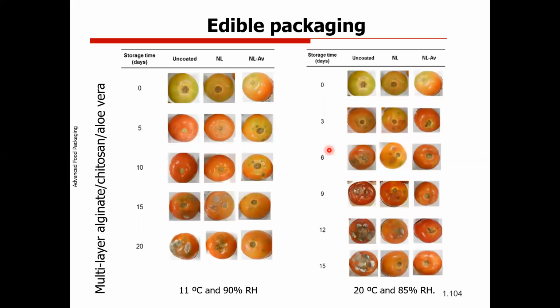This is in tomatoes. In this multi-layer it was alginate, chitosan, and in some cases we used aloe vera as active compound. You can see here uncoated, without aloe vera, and with aloe vera at 11 degrees and 20 degrees, because they are normally the conditions used to store tomatoes, and you can see that there is a clear effect of the multi-layer system, mostly with aloe vera because of some antimicrobial and antioxidant compounds that are very well known. And you can see here that we have this effect in the tomatoes, and we are able to increase shelf life with these kinds of technologies.